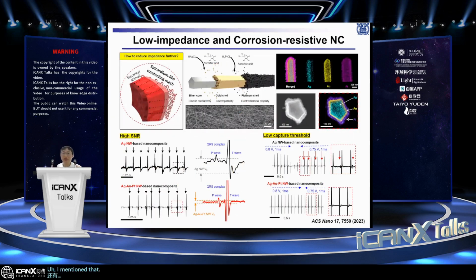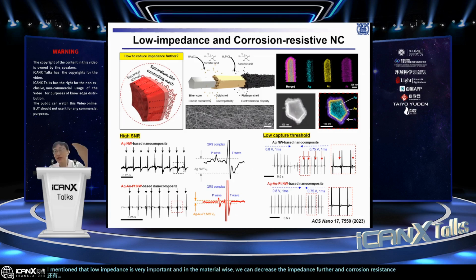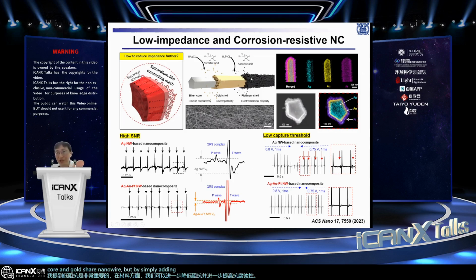I mentioned that low impedance is very important, and material-wise, we can decrease the impedance further and increase the corrosion resistivity further. Previously, we used the silver core and gold shell nanowire, but by simply adding a platinum shell, the impedance can be even lower, and platinum has very high corrosion resistance in comparison to silver and gold. So over long-term implantation, platinum maintains its original low impedance and original electrical property.